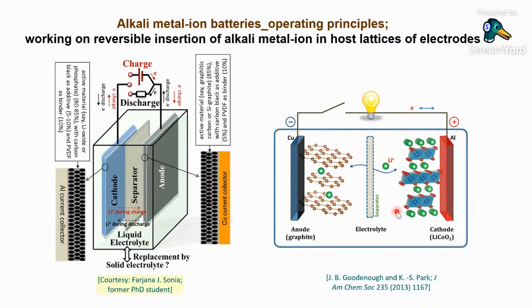For example, during charge of a lithium ion cell, the lithium ions move out of the cathode side, which is lithium cobalt oxide or its variants, and then get hosted in the lattice of the graphitic carbon, which usually behaves as the anode material. And the reverse happens when we are discharging the cell, and that is withdrawing power stored in the cell. So as we can see, the charge carrier ion, here lithium ion, for a sodium ion cell, this can be sodium ion, and so on. They get inserted into the lattice of the electrode materials and again come out.